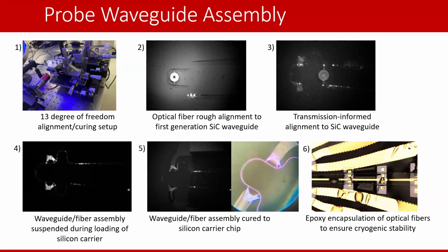There's all these wonderful hand micrometers where we can bring the tapered fibers close to the waveguide. These are actually images from previous waveguide designs. You'll notice that this bend is here because when you cool down this probe system, there's enough thermal expansion that you need this strain relief bend to prevent the optical fibers from actually ripping the silicon carbide apart. Because while it's a strong material, there's only 400 by 400 nanometers of it in a waveguide, and so there's only so strong that it can be. And so yeah, this is the process of assembling this thing together.